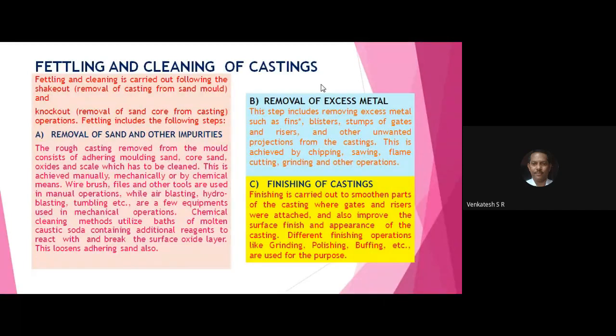In the shot blasting machine, there is a provision to shoot small balls of 2 millimeter or 1 millimeter diameter, which impinge and hit the casting surfaces, so that whichever sand particles stick to the surface of the castings are removed by hitting the surface with the small steel balls. In the same way, in the sand blasting machine, they hit the casting with sand particles, so that any dust or extra material present on the surface, such as burnt paint or burnt coating on the casting, is removed by blasting with the sand.